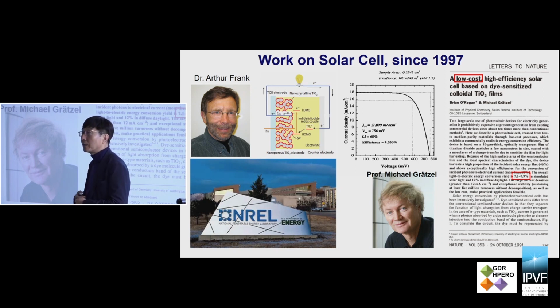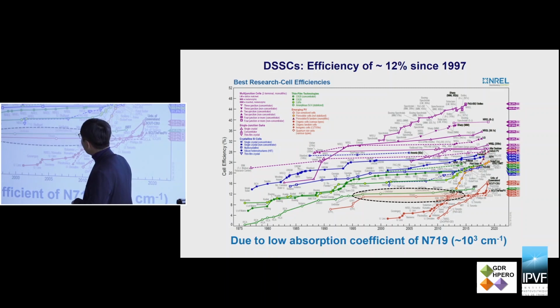And as I mentioned, the publications in photovoltaics were not that many because the silicon solar cell price is very high. So the issue in photovoltaics is how to reduce the cost. So Michael Grätzel published the low cost dye-sensitized solar cell. However, the efficiency was a little bit lower than the silicon type or the conventional solar cell structure, about 7 to 8%. Then the efficiency slightly increased to 10 to 11% in 1997.